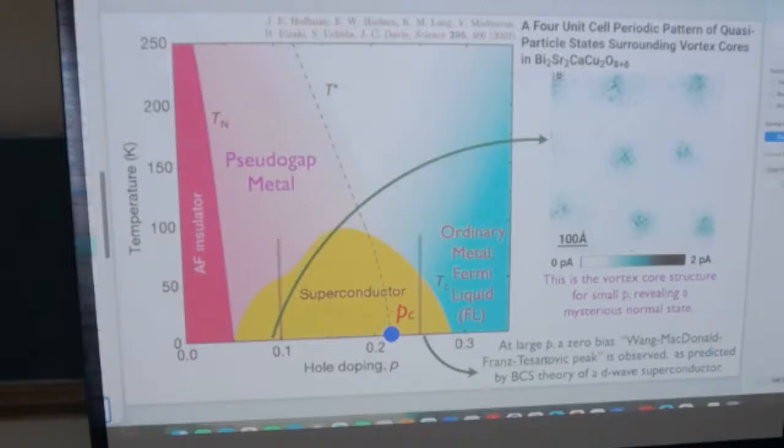Here, if you do the analogous theory for BCS, Landau-Ginzburg, or Bogoliubov-de Gennes, you get a peak. And you do see the peak over here, but you don't see it here. So that's, I think, very strong evidence already that there are two different metals underlying the low doping and high doping regimes, and so perhaps in the metallic state at least, there's a quantum critical point.